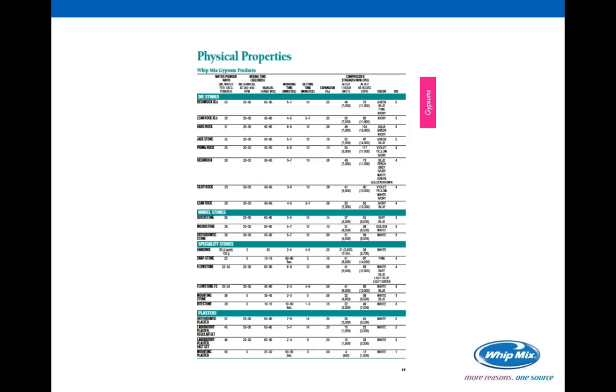the expansion, which once again is reported at 2 hours, and you will have both wet, which is a 1-hour compressive, and dry, which is a 48-hour compressive number that's there, plus the color for those of you who are interior decorator types, and you will also have the ISO rating for that particular stone.